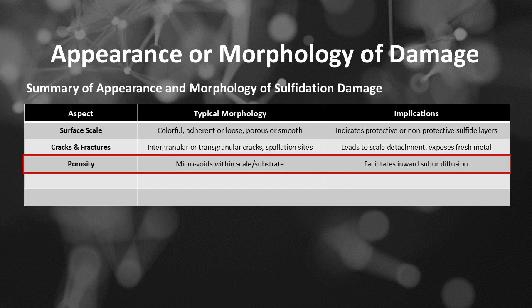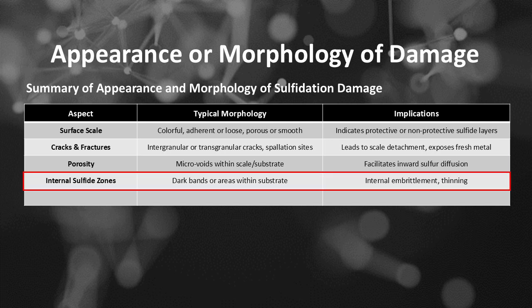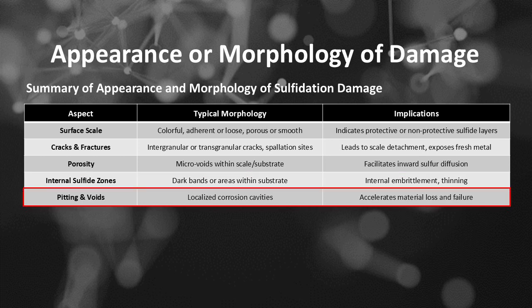If the aspect is porosity, then typical morphology is microvoids within scale or substrate, and its implication is that it facilitates inward sulfur diffusion. If the aspect is internal sulfide zones, then typical morphology is dark bands or areas within substrate, and its implication is internal embrittlement and thinning. If the aspect is pitting voids, then typical morphology is localized corrosion cavities, and its implication is that it accelerates material loss and failure.